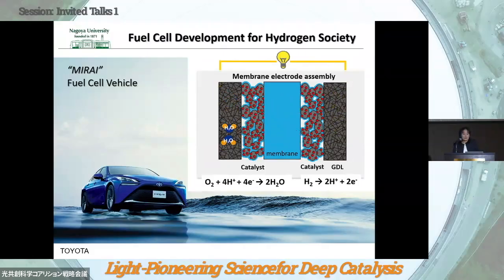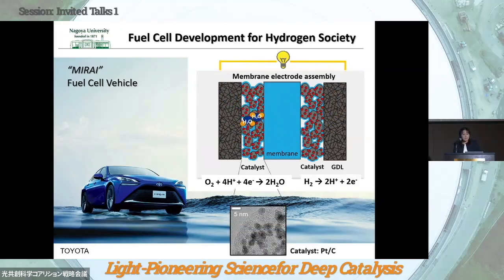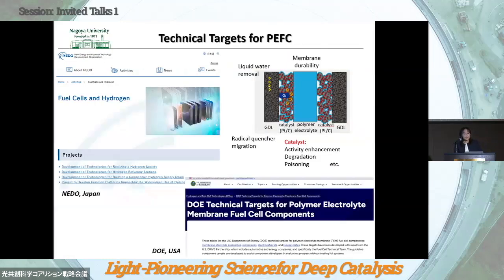There are two types of catalysts in the membrane electrode assembly of the PEFC. One is for oxygen reduction at the cathode side, and the other is for hydrogen oxidation at the anode side. Platinum is essential to promote the catalytic reaction on the cathode side, and we always use platinum or platinum bimetallic catalysts on the cathode side.